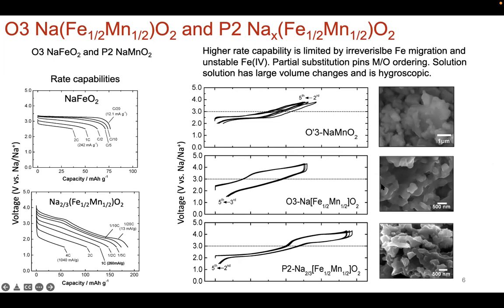Okay, so one of the issues with working with this material that people have been trying to combat, of course, is that these materials are quite hygroscopic, and typically, you think, okay, well, can I just work in a dry room and dry this off? The issue is once you synthesize the material, if it's out in the air and it's hygroscopic, not only will the H2O molecules adsorb, but they can also intercalate within the layers.